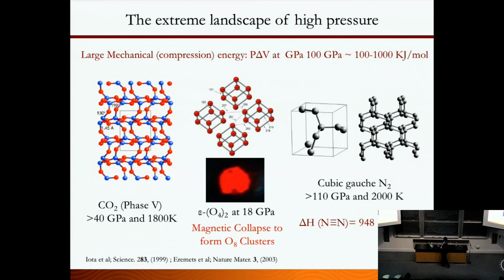All right, so let me give you a few examples so that you have an idea of what's really happening when you apply pressure. When you apply pressure, the P delta V compression energy can be comparable to the bond energy of those materials. You can generate 100 to 1,000 kilojoules per mole by going to really high pressure, like roughly 100 GPa.